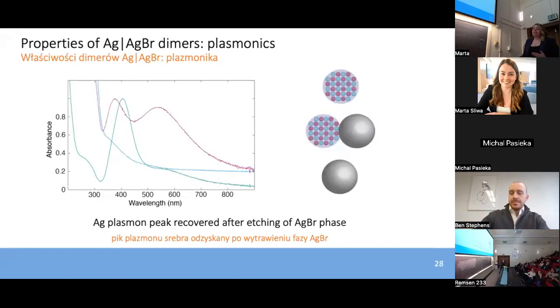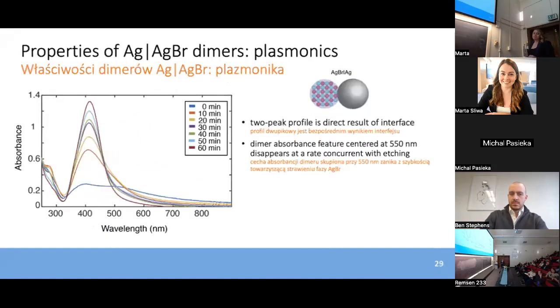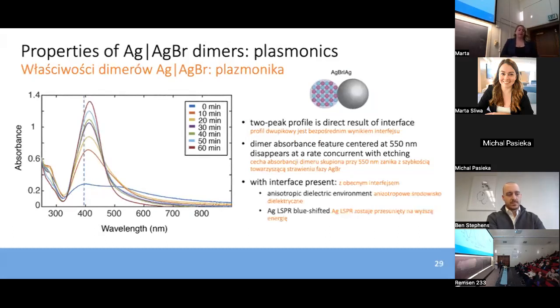So this was our initial indication that the two-peak profile is indeed a result of the presence of the interface in that dimer morphology. We were also able to systematically monitor the evolution of the absorbance spectrum during the etching process by taking time-stamped UV-vis measurements, and with this further confirmed that the two-peak profile is caused by the interface in these morphologies. So you'll notice that when the dimer is intact, we have that two-peak profile here. There is a peak that we ascribe to the silver plasmon of the silver phase in that dimer, and it lies blue shifted with respect to where we would expect a standalone nanoparticle to come up at roughly 405 nanometers.